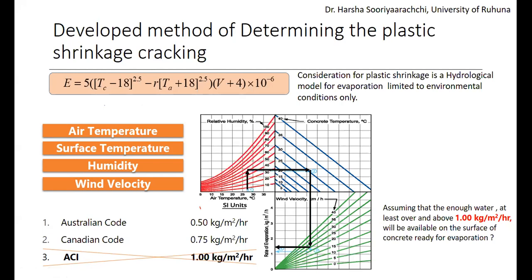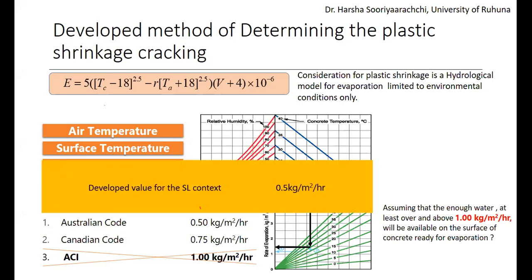ACI suggested that if it goes beyond one, then there will be a risk of plastic shrinkage cracking. But for the context of Sri Lanka, Dr. Suraj identified, it also changes with the cement type. But basically, if it goes beyond 0.5, then there will be a risk of crack formation. So if you want to reduce the plastic shrinkage cracking for our particular case, we can take measures to reduce air temperature. How can we reduce the air temperature?